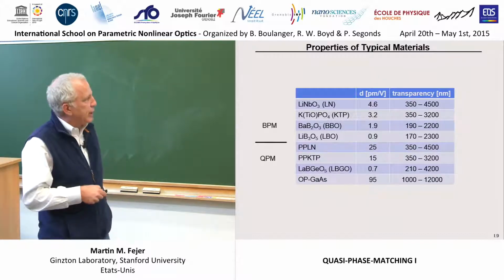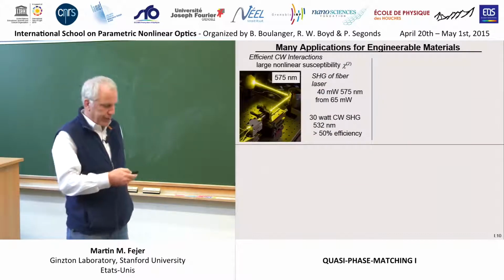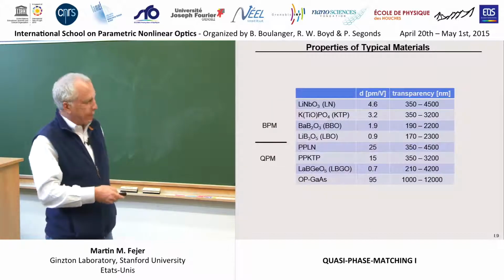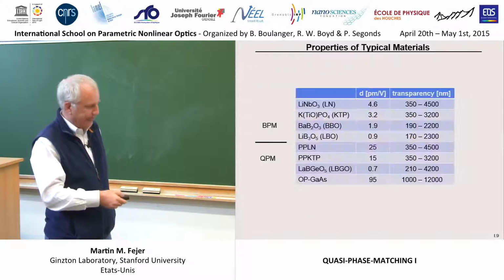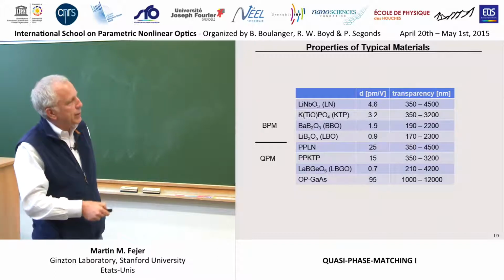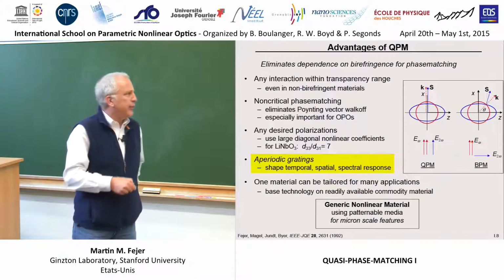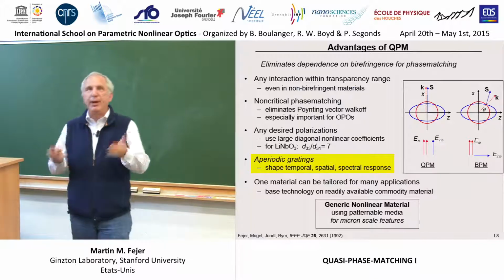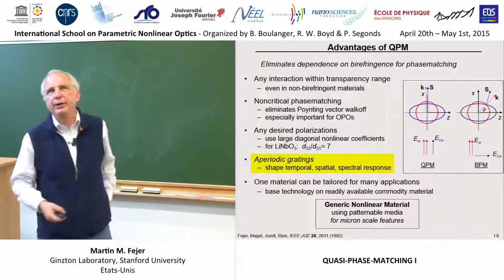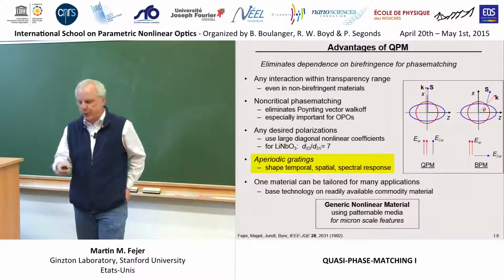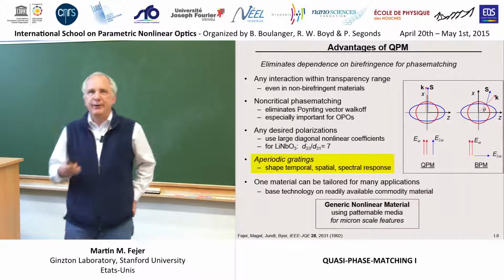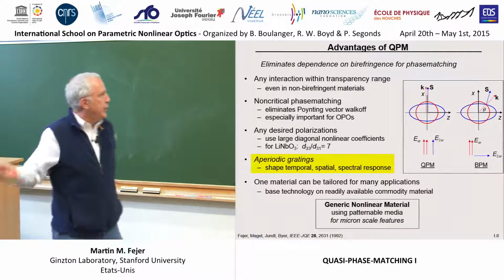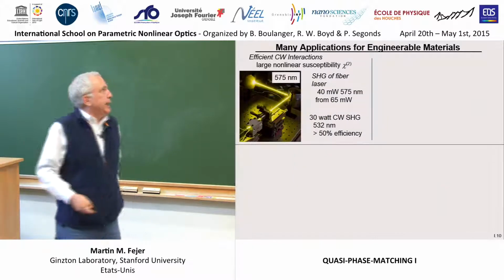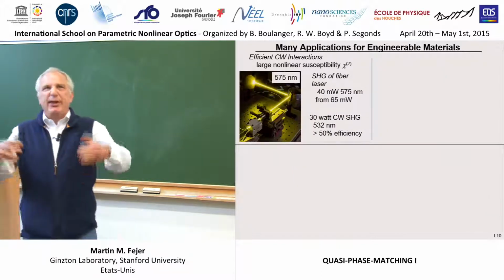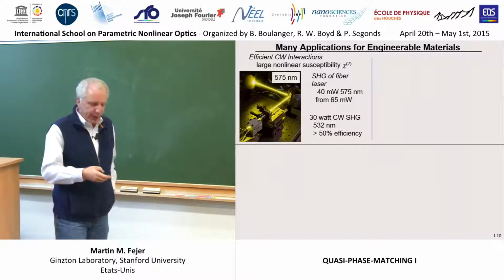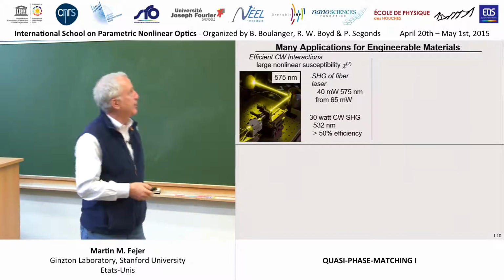And at the other end of the spectrum, orientation-patterned gallium arsenide extends transparency well into the mid-infrared. The 3-phonon peak is around 12 microns, and you can go much farther than the limitations imposed by multi-phonon absorption on the common oxide ferroelectrics. Okay, so just a snapshot of a few of the kind of things that I hope we'll have time to touch on over the course of the next couple of lectures.